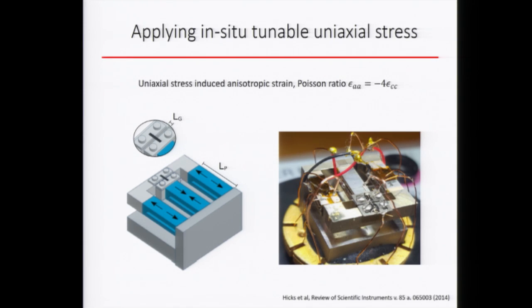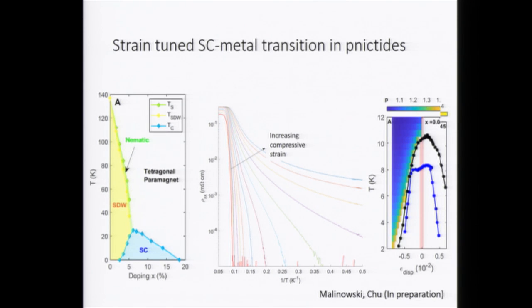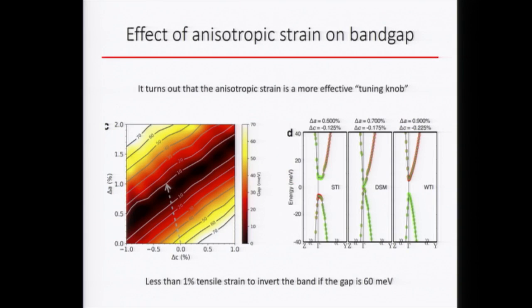Right, so this is an actual picture. We bought some from the company that was started off by Cliff Hicks, but we also custom made this so that it can fit onto different kinds of sample environments. And just as a side, we used the same device to enhance the nematic order in the iron-based superconductor and induce a superconductor to metal transition with strain. I'll be happy to discuss with you offline if you're interested.